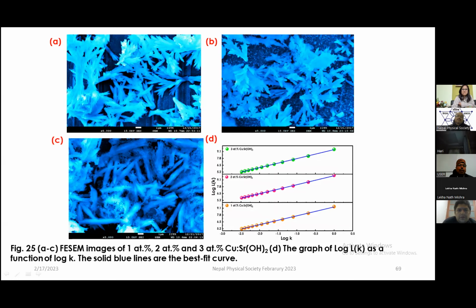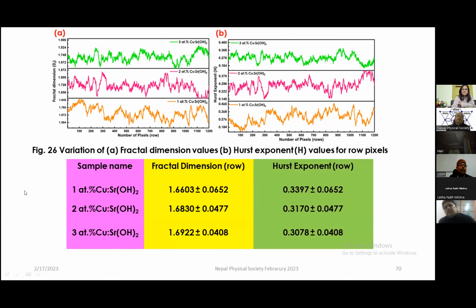Then we have to calculate the fractal one. So one can see the fractal dimension here and the number of pixels. So that has been calculated. And the Hurst exponent is just opposite to that one. See here that the fractal dimension is the highest value. At the same time, one can see this is 2 minus df, so it has the lowest value.